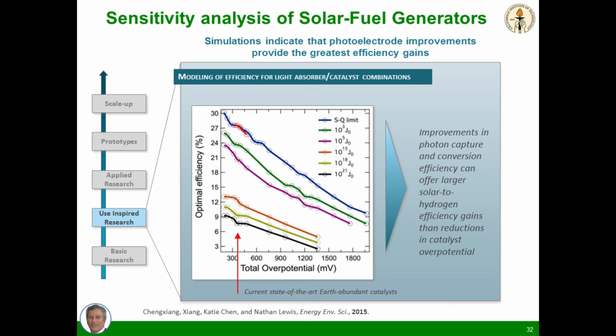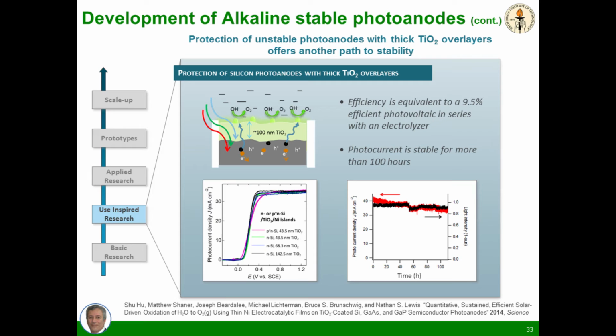In order to do that, we went back 20 years or more to a discovery made for another reason at Intel. TiO2 is the ingredient used in sunscreen, and it's a blocking layer. But that blocking layer is not supposed to pass holes or electrons because it's insulating. We inadvertently deposited by atomic layer deposition that TiO2 on top of a silicon substrate and found that it was not insulating, that it passed light but let electrons and holes go through the material. And indeed, it passed a lot of current while protecting that underlying silicon from oxidation.